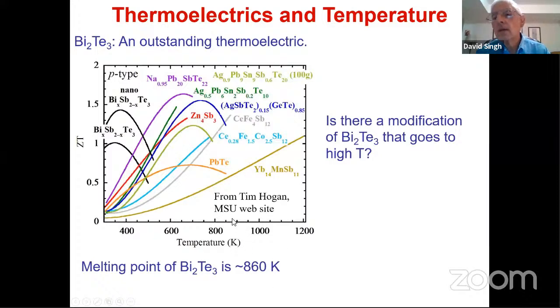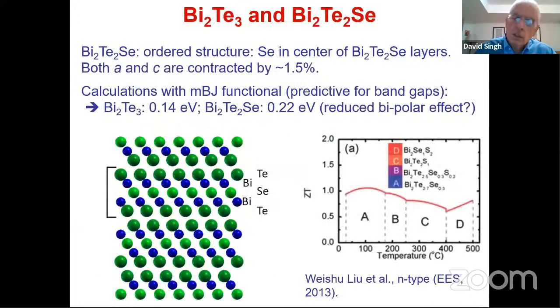And so why is that? The reason is known. The band gap of bismuth telluride is small, and if it had the same band structure and the same properties, but a larger band gap, the ZT would be higher. So our idea was, let's alloy with some different elements and see if we can make a better bismuth telluride. We thought of selenium, and other people did too.